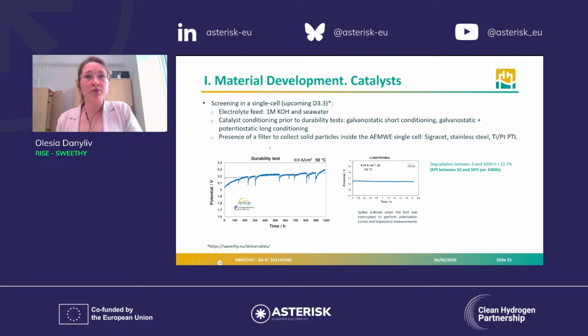I cannot show you much more than this, but we are doing the durability test, and what we received up to now is that the developed catalysts show good durability during 1,000 hours, and the degradation rate was not more than 13%, which lies very good in the KPA that we defined in the beginning of the project. So this gives us promising results for the developed PGM-free materials for seawater application.